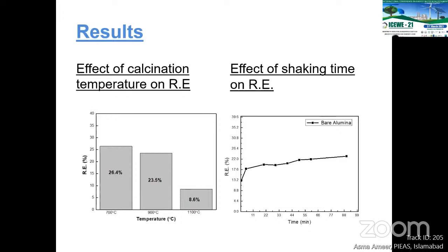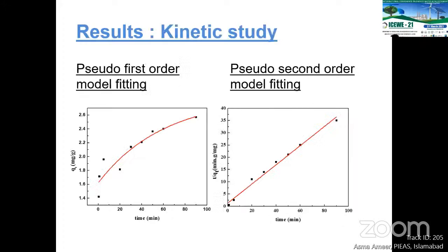Next graph is the effect of shaking time on removal efficiency. As the shaking time is increased, more and more contact occurs between alumina and lead ions, and with increase of shaking time, all the sites are being occupied with lead ions. But after about 60 minutes, when all the sites of alumina are filled with lead ions, no further increase in removal efficiency occurs. This is basically the equilibrium time for this study.